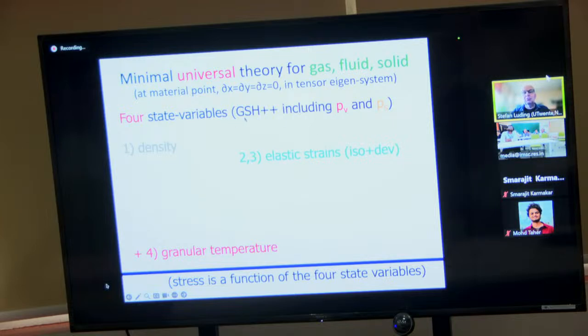GSH stands for Granular Solid Hydrodynamics. It was developed about 20 years ago by Mario Liu, and the plus means I added a few things to it. Since my expertise, and what I have done for more than 20 years, is particle simulations, one plus stands for the particles and the particle model, and the second plus stands for the stochastic events, which are the PV and the PS, the probability for isotropic and shear plastic events in an otherwise elastic system. That's what I mentioned in the previous part of my talk already. Then you have density and elastic strains as state variables, and the granular temperature. Stress can be expressed as a function of the 4 state variables, so stress is not new, or you invert. Density, elastic strain, granular temperature, I will continue with.